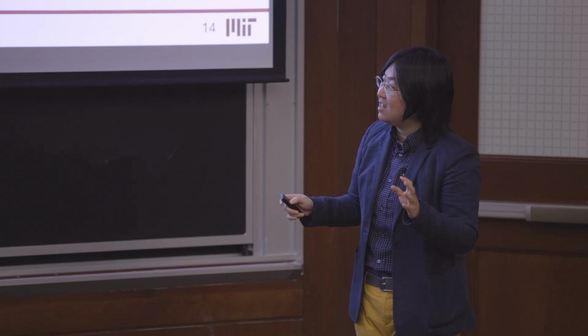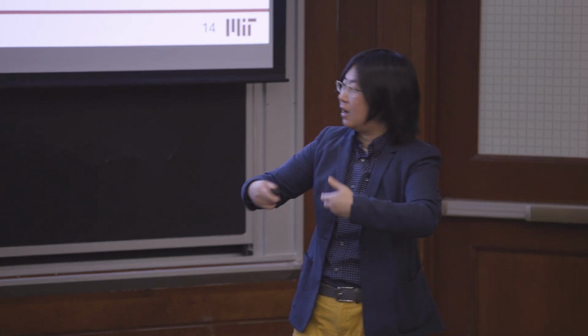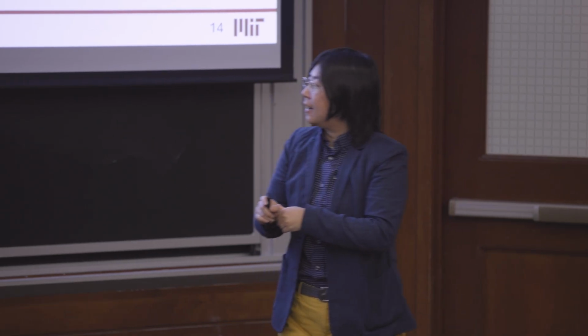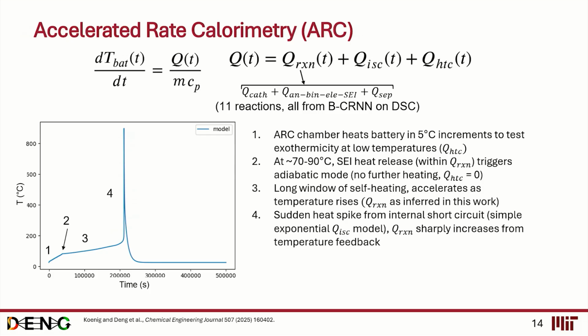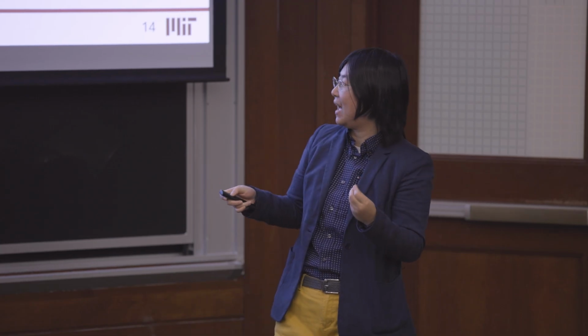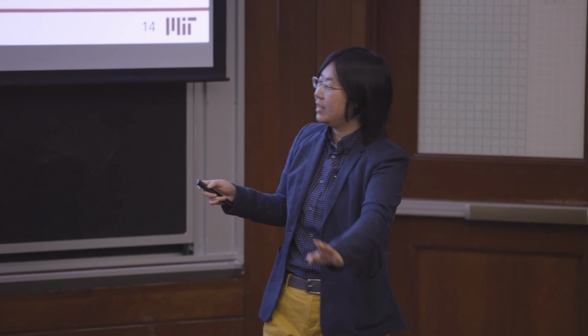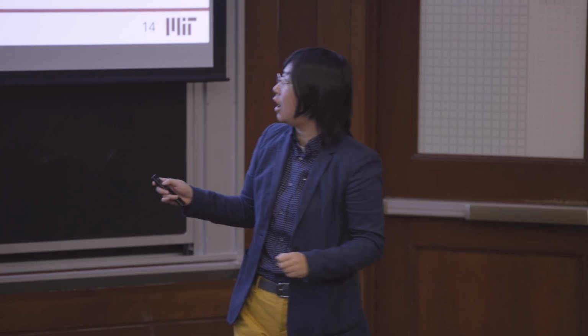If you wait long enough, such heat accumulation and self-heating would eventually trigger the internal short circuit by the melting down of the polymer separators, and then you see the battery catches fire. And because now we don't have external heating, it's an adiabatic environment. This whole process captures the thermal runaway of the batteries. And eventually it would cool down after everything's burned off.